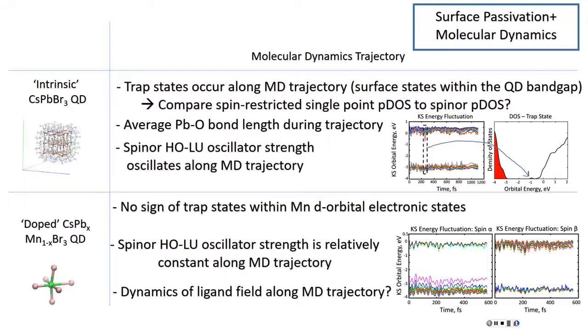Actually, I think he was doing the autocorrelation function first, and then making a Fourier transform from the autocorrelation function to get the spectra, which gives you some kind of frequencies, right? Which would correspond to the normal modes, either acoustic or optical modes, collective motion, which will be really related to these lead oxygen oscillations. And also you probably can find in the literature these lead oxygen normal modes for the surfaces or something.